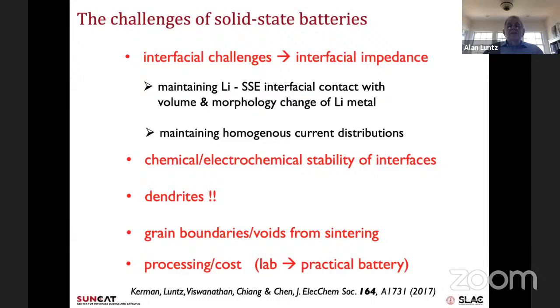The way you make these solid state electrolytes is you sinter together a bunch of small particles. So there can be voids, there can be grain boundaries. All of these things can affect the conductivity, the lithium-ion conductivity through these electrolytes. And then there's also the issue when you want to go to a practical battery from a lab. Can you do scalable processing? Can you do that cost effectively and so forth? So from a practical point of view, there are still unresolved issues about this.